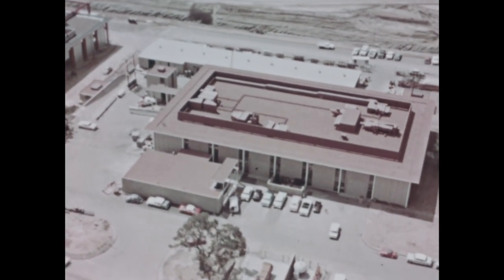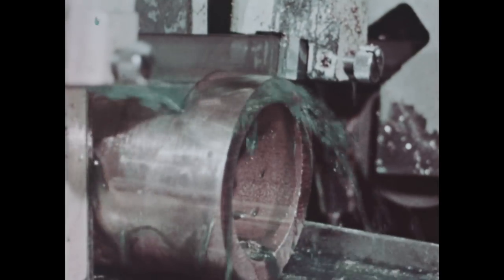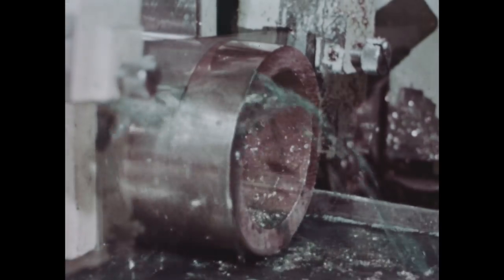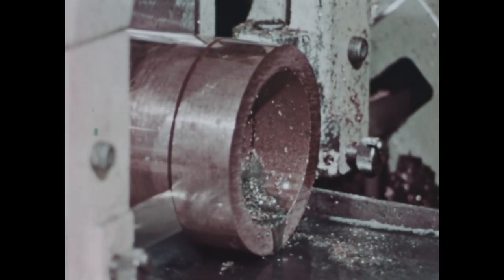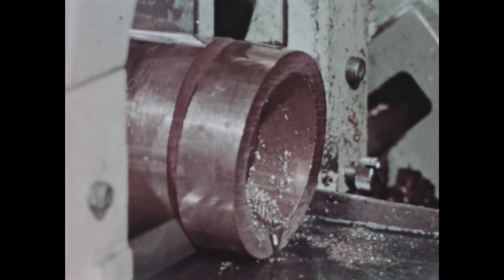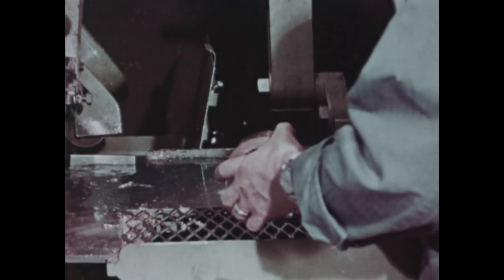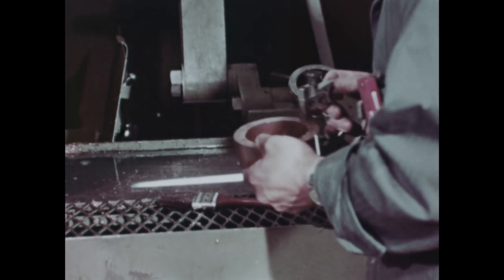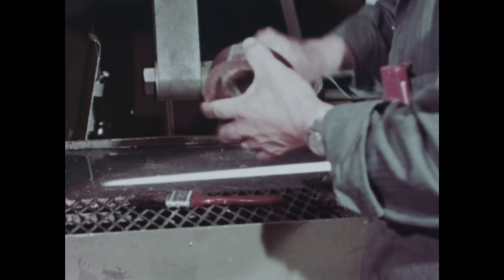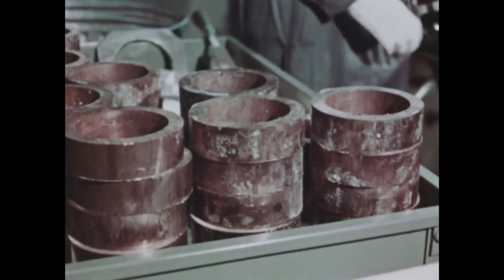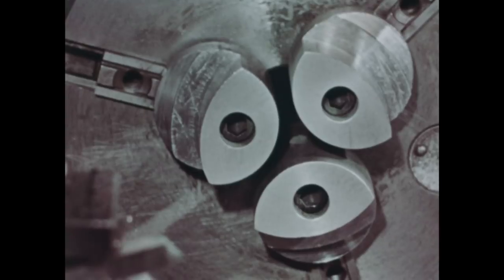Fabrication takes place at the Stanford linear accelerator site. It begins with the rough finishing of copper cylinders and discs which will make up the disc-loaded waveguide. Ten foot lengths of extruded round copper pipe are cut into cylinders approximately one and a quarter inches long. They are checked for rough length and deburred prior to machining. The cylinders are then rough machined to within ten thousandths of an inch of their final dimensions on all surfaces.